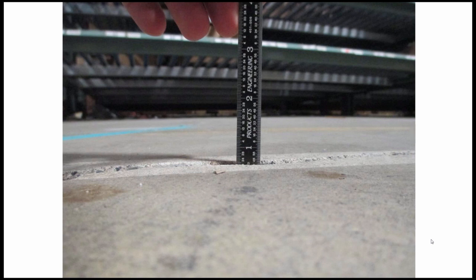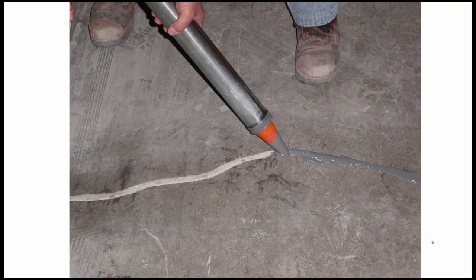And of course, quality control is important. Usually what I do in these situations is specify the saw cut to be about an inch deep. What I find in the field is that gets me typically anywhere from 3/4 of an inch to an inch. And it works out pretty nice, because if it's less than 3/4 of an inch, the contractor tends to not push back too much if I call them out to cut it deeper. And if it's greater than 3/4 of an inch, in our experience, we tend to get really good performance.